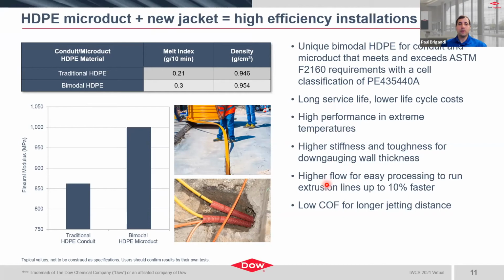And this higher flow has really enabled up to 10% faster processing on typical lines. So combining this material plus the jacket, we're looking at improving that coefficient of friction as well. And this combination provides even longer jetting distances for field installations. So really looking at this from both aspects, from the wire and cable side on the jacket, as well as from the conduit microduct side, and combining the material solutions.